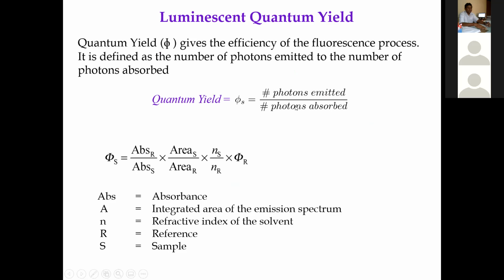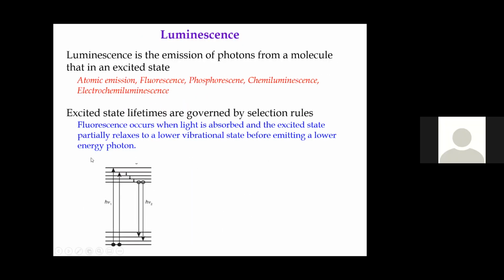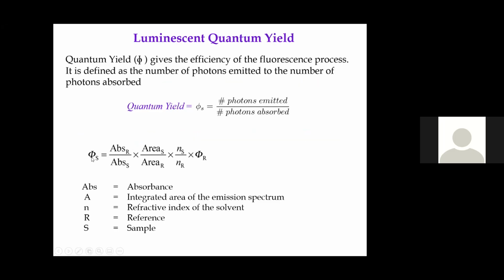It is something like, if you give 100 photons, which is 100 photons absorbed, and if the material gives 100 photons back, we call your quantum efficiency 100% or 1. So there is an indirect way of measuring the efficiency of these materials. You use the absorbance and the integrated area of the emission and the refractive index of the solvent, and we use a reference, and then you can measure the quantum yield of the sample. So those are the basic three properties we measure: the absorbance, the luminescence, and the quantum efficiency.